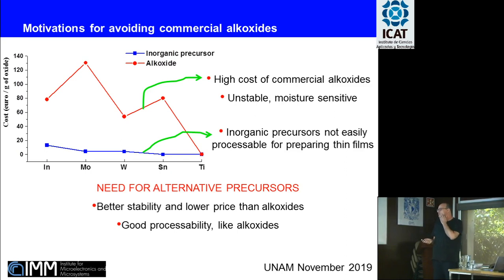So the idea was to develop some alternative precursors having better stability and lower price than alkoxides, like inorganic precursors, but good processability like alkoxides. So, cheap and stable precursors giving uniform films with a good adhesion to the substrate.